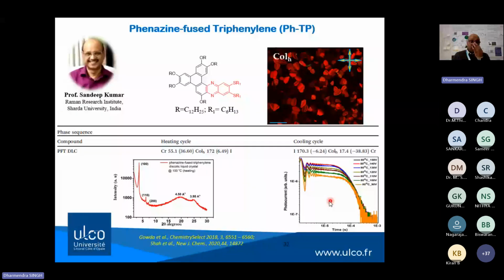Why did I tell you this? Because in our next investigation, we came across a very interesting fact. We had already investigated this triphenylene-based system in our last results. The idea was to induce ambipolar charge carrier mobility in a system. Because this system only showed hole mobility, we fused a phenazine unit into the triphenylene system to get ambipolar charge carrier mobility. These materials were characterized by polarized optical microscopy, DSC, X-ray, and time of flight techniques. Here you could see very nice photocurrent curves.